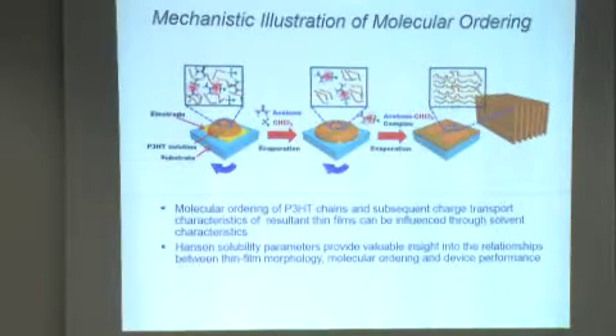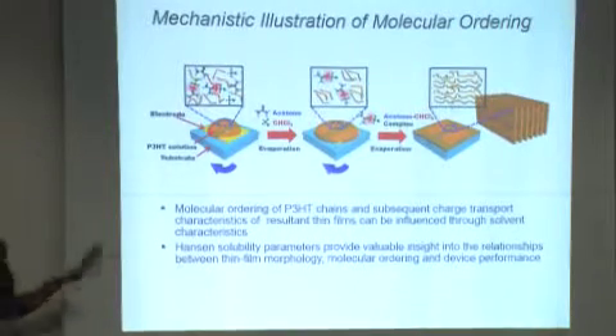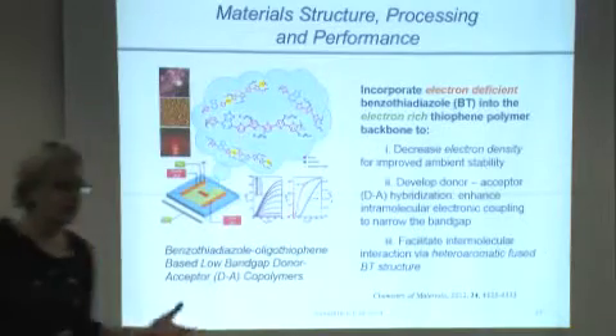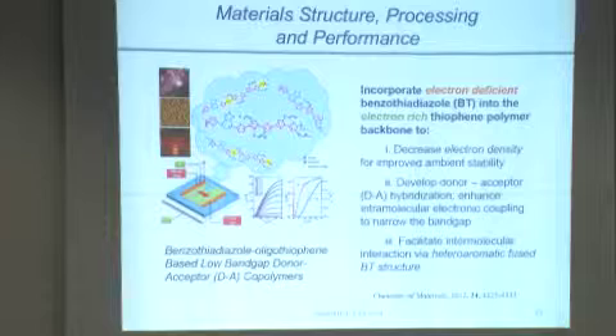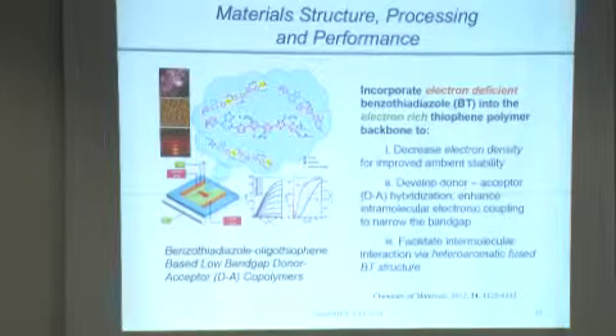Right, so mechanistically, we think that there is ordering of the P3HT chains that's induced by the poor solvent. And certainly, the ordering of the polymer chains can be influenced through solvent characteristics, and we may be able to use Hansen solubility parameters as a way of being able to gain more insight into the relationships between thin film morphology, molecular ordering, and what we're ultimately interested in, device performance, so that we can now couple these together for an application.